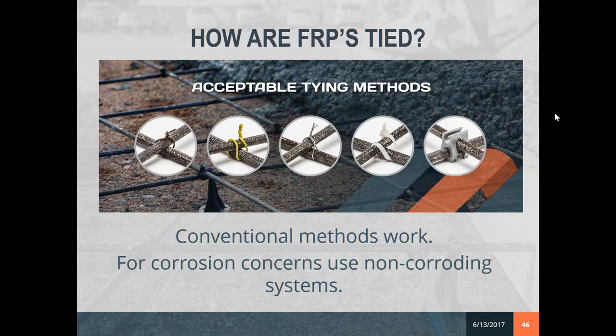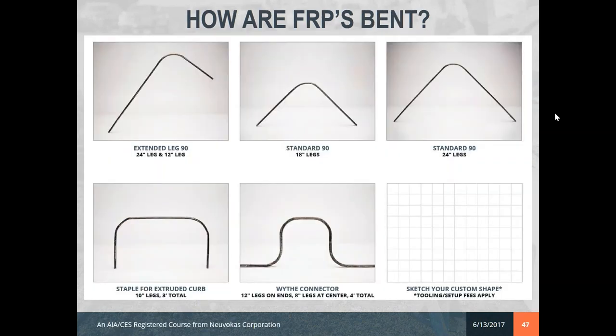That's pretty funny. But what they should do is bend that down and tuck it up under, or cut it off. So in your specifications, if you're allowing just plain wire ties, you'd really want to make sure that that gets done. Otherwise, you get all these little rust spots. When that little uncoated wire begins to rust, it's the first thing that rusts all the way through, again allowing a capillary of water to seep down to the steel reinforcement and start corroding it. With FRPs, another advantage is you don't get that.